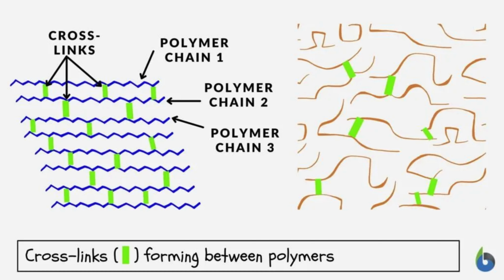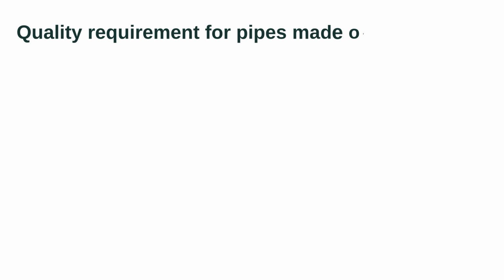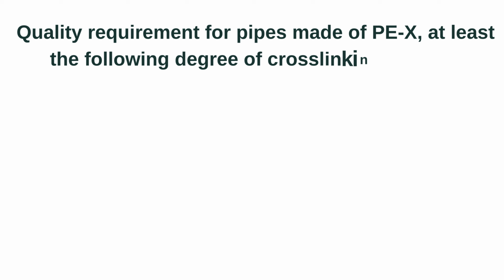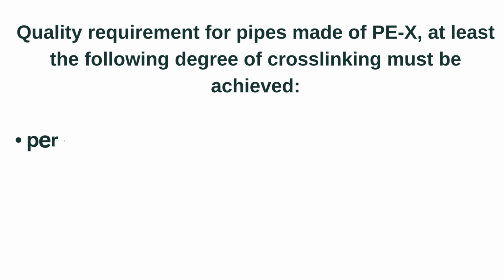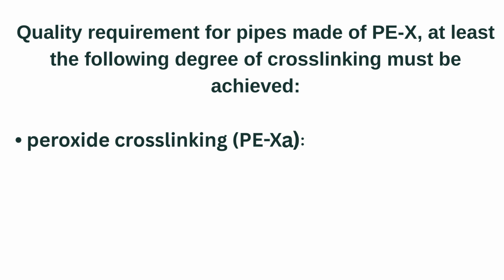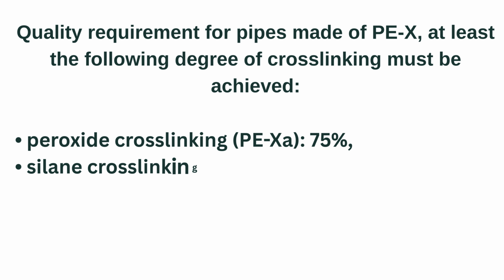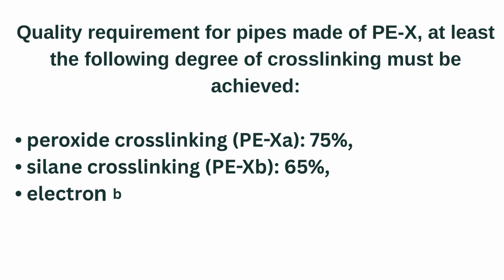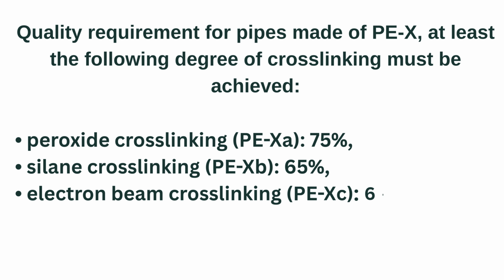The degree of cross-linking, and hence the extent of the change, is different in intensity depending on the process. According to the quality requirement for pipes made of PEX, at least the following degree of cross-linking must be achieved. In peroxide cross-linking, PEXA, 75%; with silane cross-linking, PEXB, 65%; with electron beam cross-linking, PEXC, 60%; in azo cross-linking, PEXD, 60%.